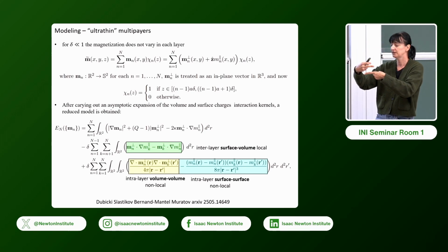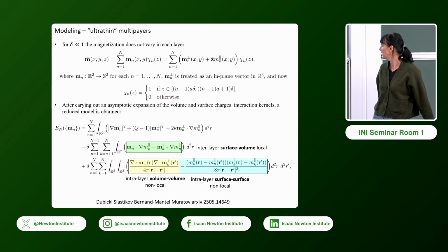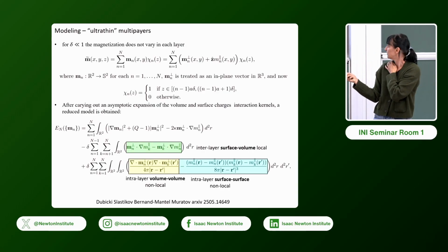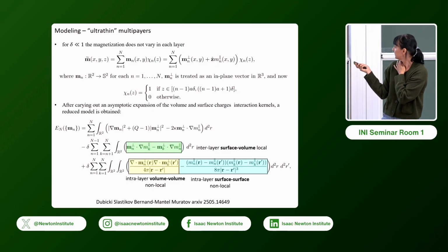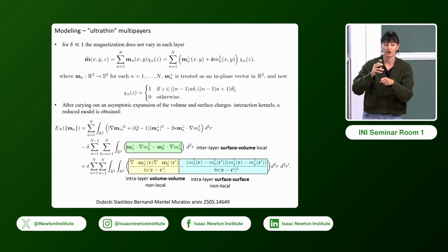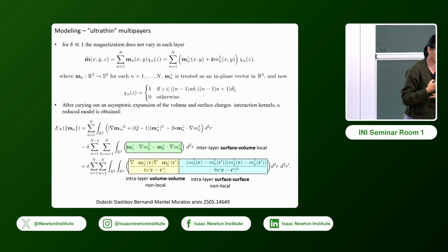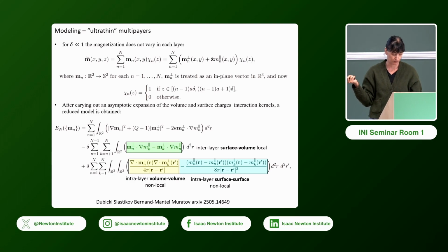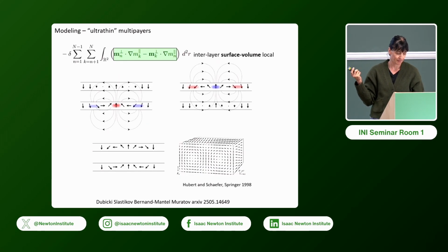And if this rotation is in such a way that M parallel is anti-parallel, here we are going to obtain twice this term. This is going to become +1, twice this term, and this is going to be equivalent to a DMI term, favoring the rotation with the opposite chirality in both layers. And this is also a local term, so this is a non-negligible effect.